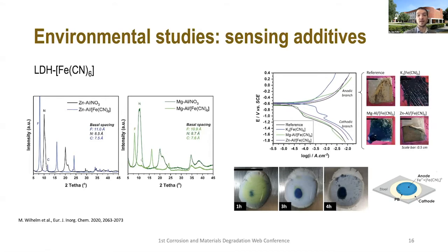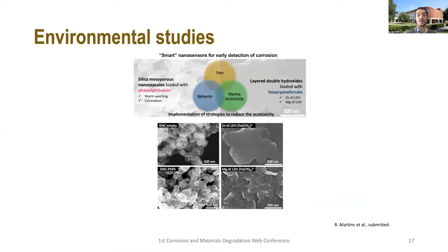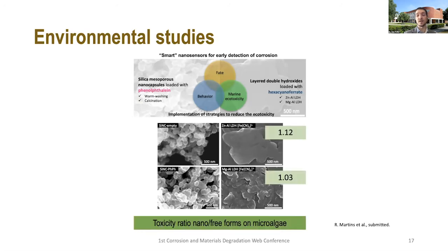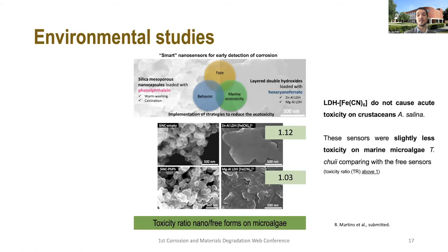So why am I presenting these additives here? Because if we want to change coatings, we also have to be sure about the environmental impact that these materials can have. So our colleagues in the environmental studies were trying to see what would be the effect of the intercalated or immobilized and the free sensing compound. They saw for the LDH, similar to the MBT, that the LDH was helping reduce the toxicity effect of the hexacyanoferrate, which was not very high compared to MBT.